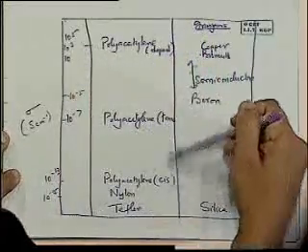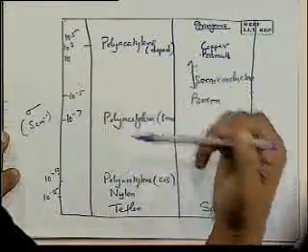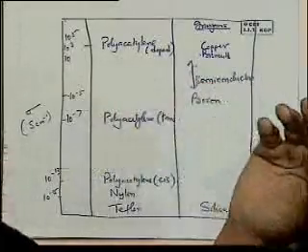Undoped, depending on the particular form, it's either cis or trans. It's 10 to the power minus 13 or 10 to the power minus 7. You dope it, there is a radical change in this. In fact, it is in this field of conducting polymers that the Nobel Prize was awarded in year 2000 for chemistry. And it has made a big revolution, not the Nobel Prize, but this discovery of conducting polymers has really dramatically changed because they are so easy to handle relative to the regular semiconductors. And we'll look at some of those effects in a second.